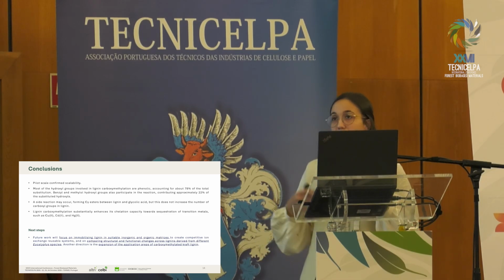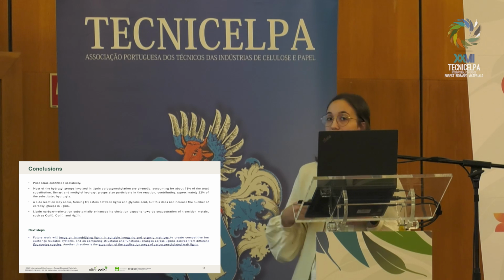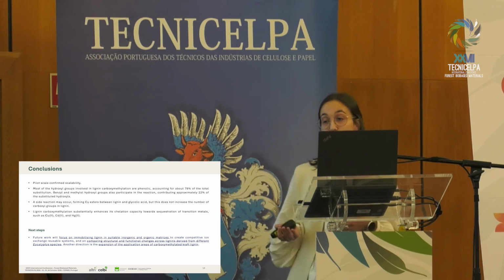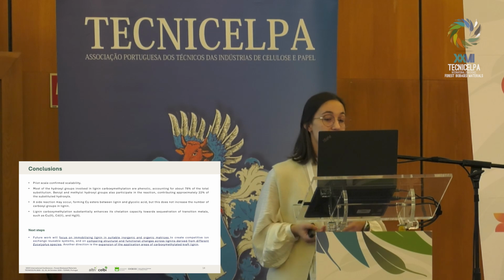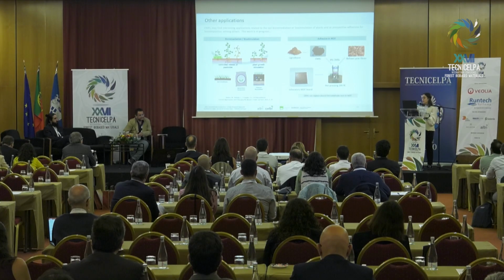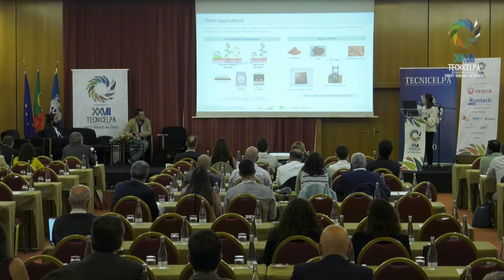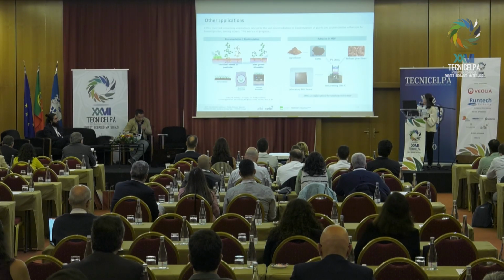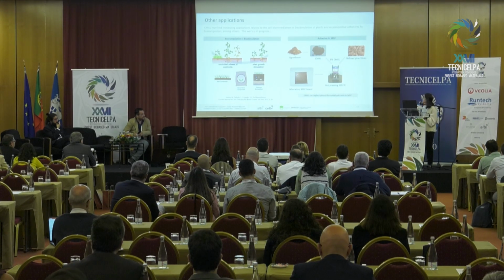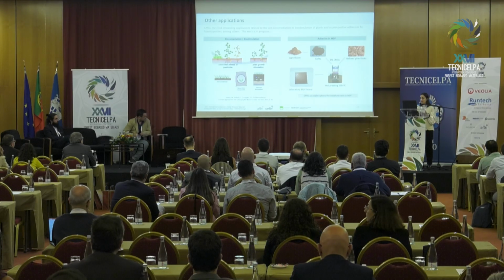In addition, this modified lignin can also have more industrial applications, such as a bio-based adhesive for MDF or other wood products. And in here, I show a simple experiment that we have done. We solubilized the carboxymethylated kraft lignin in ammonia and mixed it with refined pine fibers, and we obtained an MDF board with properties similar to the ones we have with phenol formaldehyde resins.